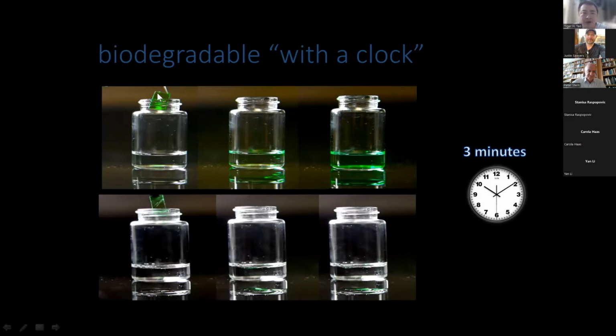we program it to dissolve in PBS very fast. As you can see, once we drop that into PBS solution, the film is going to dissolve, and everything you embedded into this film, for example any drugs, is going to release, so it controls the drug delivery. But for the bottom panel, we use some post-processing technique to increase the cross-linking degree within this film, and as you can see, it stays intact. Okay, we can control the degradation rate from a few seconds to a few weeks and longer. So that's one property we're going to use for building our silk probes.